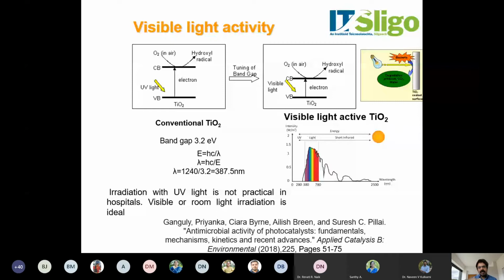If you reduce the band gap, the wavelength can be shifted towards the visible region. So that is why reducing the band gap is very, very important for photocatalysis. That is the practical way of using visible light for this type of reaction. And also, if you look into the solar spectrum, the ultraviolet light is around or less than 5%, and visible light is over 40%. So the efficiency of the catalyst can also be improved by using visible light.